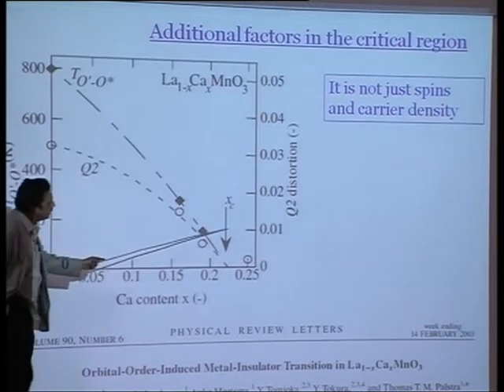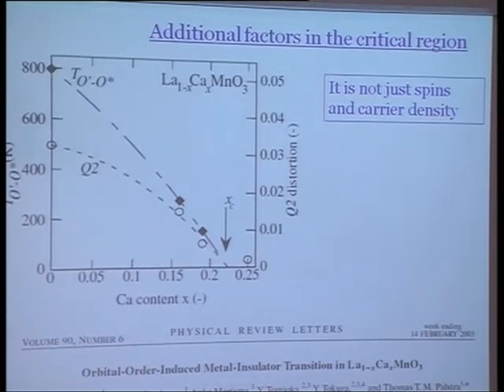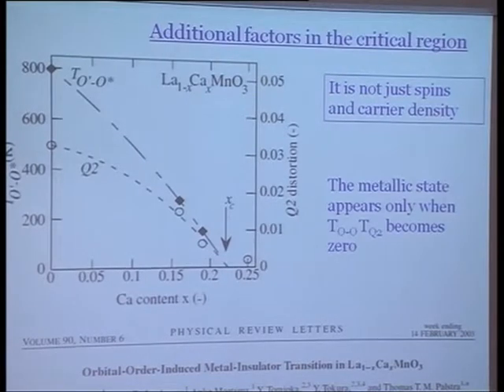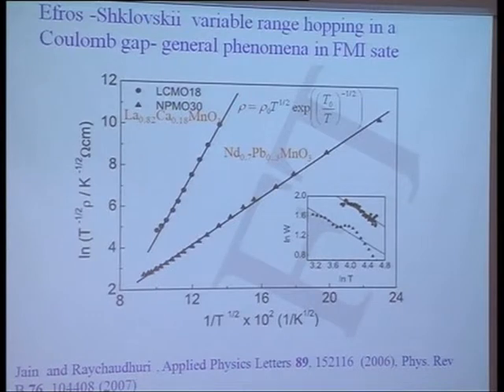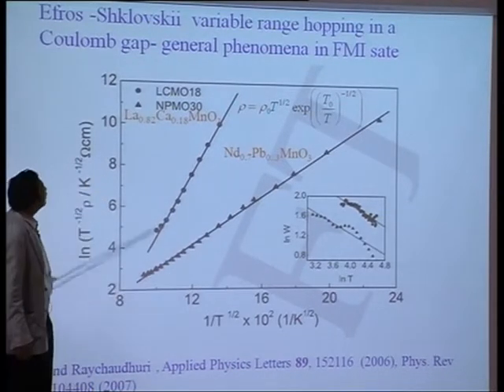You can see that this is the region where the metallic state comes in. And this metallic state comes in only when, not only do you have the critical composition, but the orbital order temperature has to go to zero, and this Jahn-Teller distortion has to vanish. So it is not only just the spin and the spin order, it is not only just the carrier density. There are important factors coming from the orbital order or disorder, and from the Jahn-Teller distortion. That is exactly what makes this field, the insulator-metal transition, a new paradigm in this class of material. There are other factors coming in which are not present in most of the other simpler oxides like NaxWO3 or phosphorus-doped silicon, where of course the valley problem is there, which is important. Now this is not the only material where you see this kind of Efros-Shklovskii system. There are a lot of other systems.